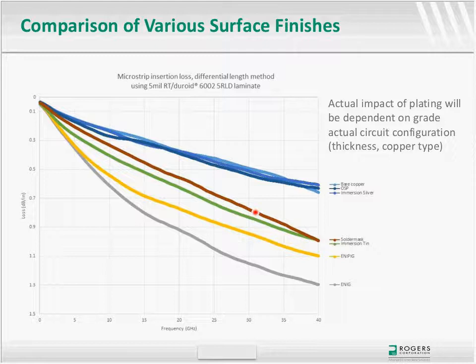So in reality, Rogers will remeasure this data to take that into account. We'll take a traditional trace with 50 ohms here, apply solder mask, and you will probably see somewhat of a change, mainly because it changes the dielectric constant, but it probably won't be as much as what we see here, because this trace was really a more narrow 50 ohm trace than it would have been here. And that's what is convoluting the problem here.